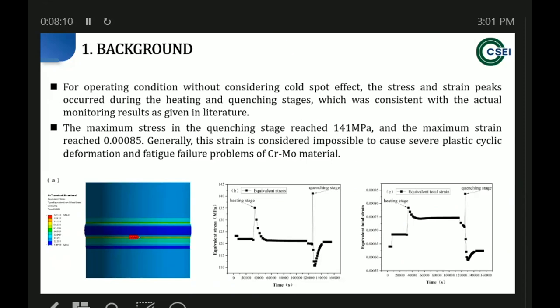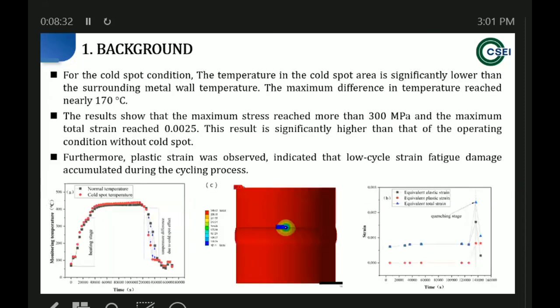The maximum stress appeared at the quenching stage, and the maximum stress is about 140 megapascal. And such stress and strain seem unlikely to cause severe plastic cyclic deformation and fatigue of this material.